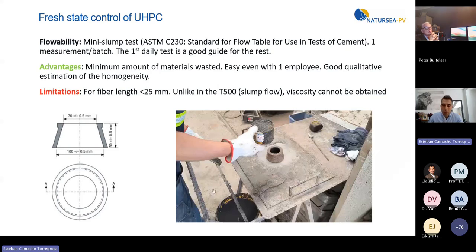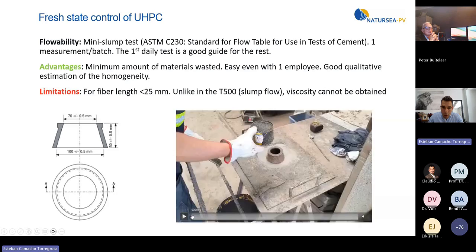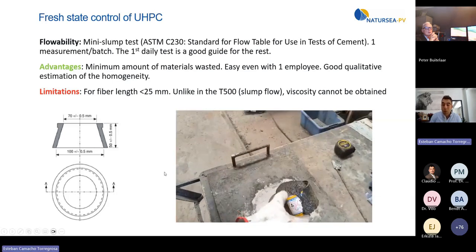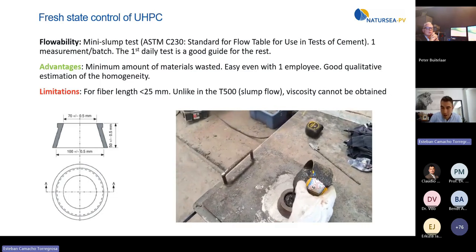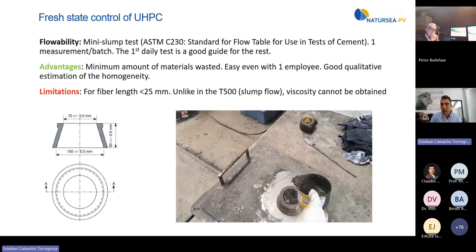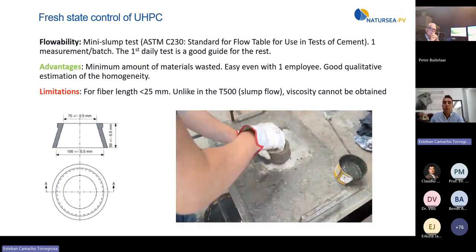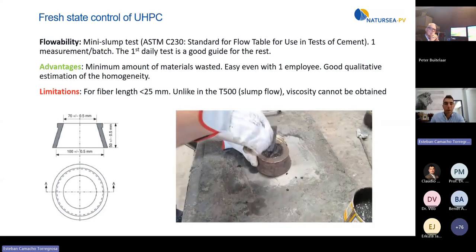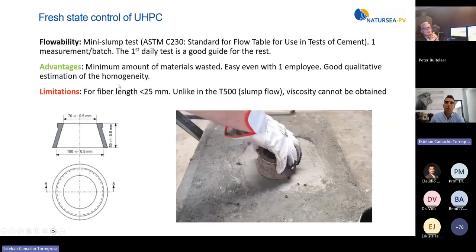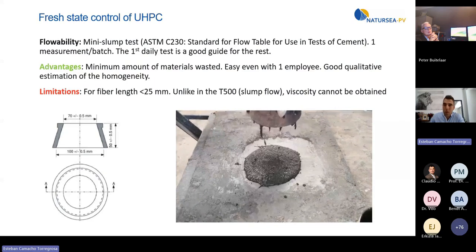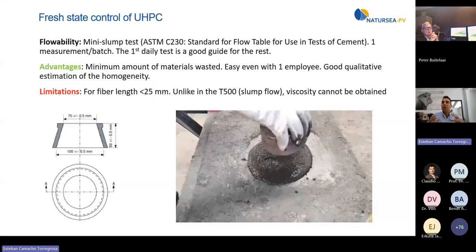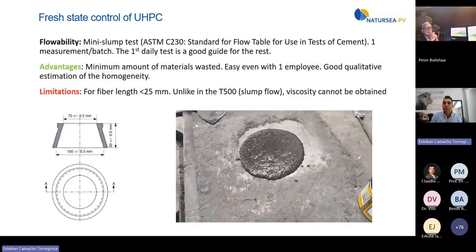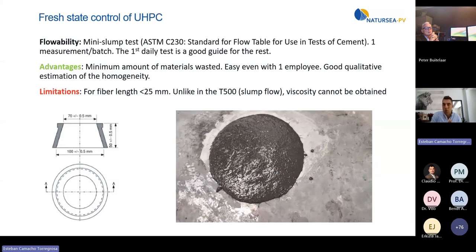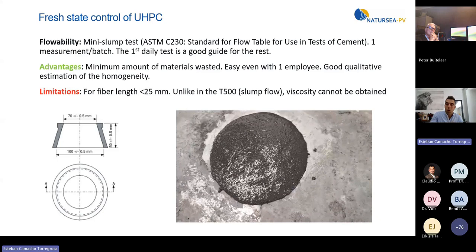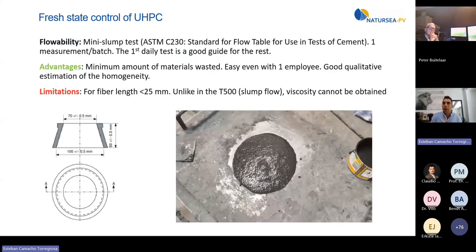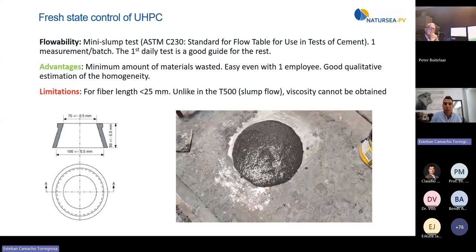Here I am showing the mini slump test cone that we use for every batch. You see the area is not very clean. This is because we do it every day. If one day we do 8 batches, we do 8 mini slumps, and we measure the diameter of the spread. What I can tell you about this test is that it's very practical, because it's fast to do. You just need 1 employee. For the slump flow, it's a little more difficult to manage with 1 person. And it's not only quantitative, because you measure, but you can also observe if there are balls of fibers or any other qualitative criteria that can show potential segregation.